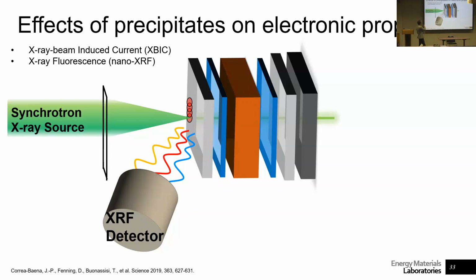So how we do this: we basically have an X-ray source that is very broad, and we have a bunch of optical settings that allow us to focus that beam into a 150 nanometer beam spot size. We can go all the way down to a couple of nanometers. If we really wanted to look at atomic scale composition, we can do that, but that takes a couple of days to set up. So we normally do the high throughput measurement, which is 150 nanometer spot size.